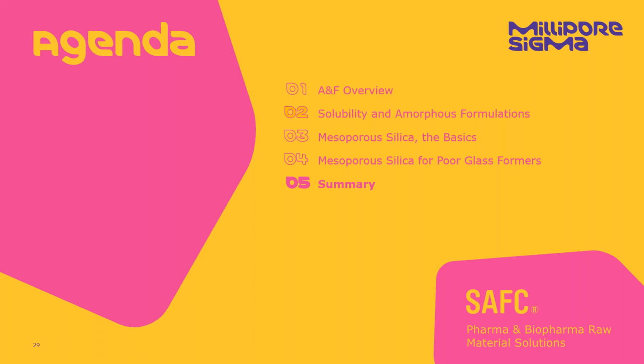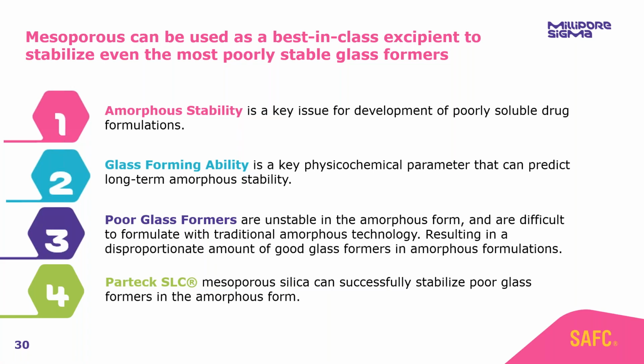But before we come on to the Q&A, let me quickly summarize what we've discussed today. Number one, amorphous stability is a key issue for the development of poorly soluble drug formulations. And glass forming ability is a critical physicochemical parameter that can ultimately predict what the long-term amorphous stability will be. Poor glass former molecules are unstable in the amorphous form, and as a result are difficult to formulate with traditional amorphous technologies. This results in a disproportionate amount of good glass formers on the market, and ultimately these poor glass formers would fail in development. With our data and with some previous data in the literature, we believe mesoporous silica is a great candidate to rescue these molecules by successfully stabilizing the poor glass former in the amorphous form.